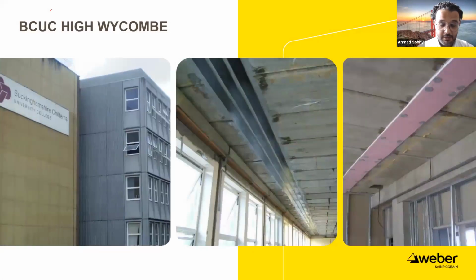This is a case study that we have done in High Wycombe, and as you can see, it's a university where Saint-Gobain efforts have come together. This is the carbon fiber plates being applied for flexural strengthening, and they have been covered by British Gypsum fire rated boards. This has given the fiber reinforced polymer system fire protection for 2 hours. This system has been completely designed by Saint-Gobain. As we said before, British Gypsum is a part of Saint-Gobain, and we applied this system under one umbrella.